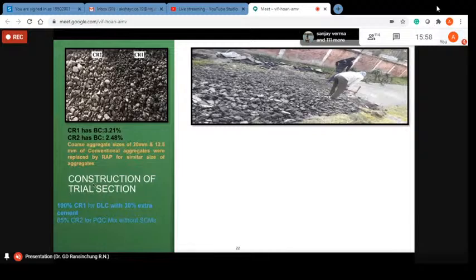For CR1, the bitumen content of the mix was around 3.21%, and CR2 has a bitumen content of around 2.48% by weight of mix. The coarse aggregate sizes of 20 mm and 12.5 mm of conventional aggregates were part replaced by RAP of similar size aggregates. And in the construction of the DLC layer, here we used 100% CR1 for DLC, with 30% extra cement added.